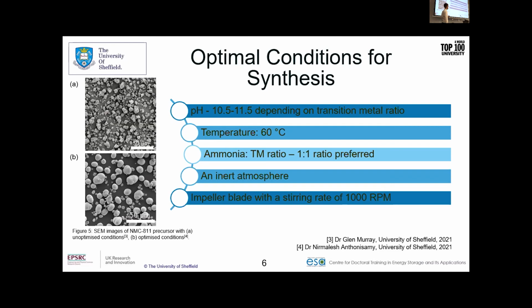We need to consider the temperature, because that also affects the thermodynamic side of the redox situation. Again, that can cause oxidation of manganese, which is particularly prone to those 3+ states and forms those 3+ phases, which disrupts that nice layered structure that we talked about and I showed you earlier. Just the transition metal ratios, but this inert atmosphere is also required. So one of the tubes in the CSTR that I showed you on the last page is a nitrogen purge. We put nitrogen at the bottom and let it bubble through, and that helps keep it nice and reduced to that 2+ manganese state to prevent those rogue Mn3+ and other compounds.